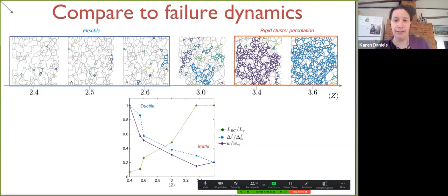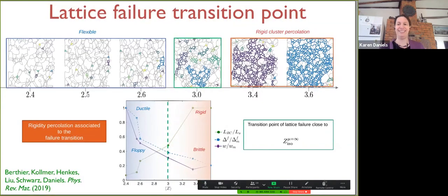Now I'm going to zoom in on the middle guy. So in the middle, this is the one that has Z equals 3, which, if it were an infinite friction granular material, which is sort of what one of these lattices is, would be the transition point. That's the isostatic point where on average, the number of constraints and the number of degrees of freedom match. So that's exactly the spot. The transition between the ductile behavior and the rigid behavior seems to be right at this spot. We don't have good error bars on this because of the way we did the experiments, but it does seem coincidentally close to 3. You can notice we don't have a 2.9, we don't have a 3.1. We didn't do those experiments. So let's zoom in on that guy and take a look at him.